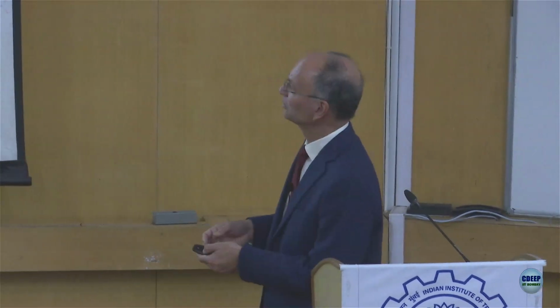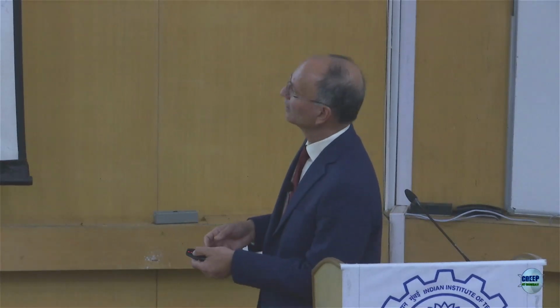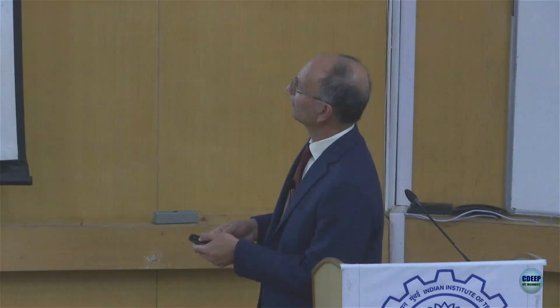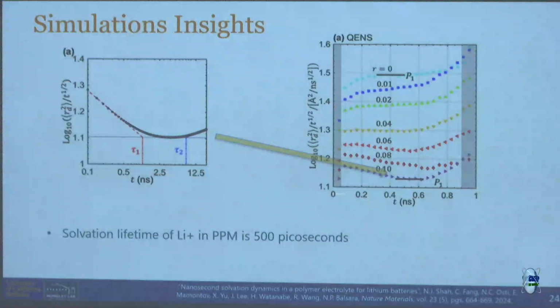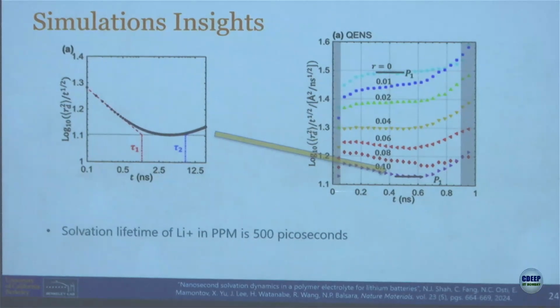I want to talk a little bit about continuum scales, because we are not interested in some 1 angstrom. When I talk about these, it's important to note the value of this x-axis. The x-axis is nanoseconds. The y-axis is 1 angstrom square per nanosecond to the half power. You're looking at angstrom level motion in the quasielastic neutron scattering experiment. And of course, because solvation is very local, that's arguably the right length scale.